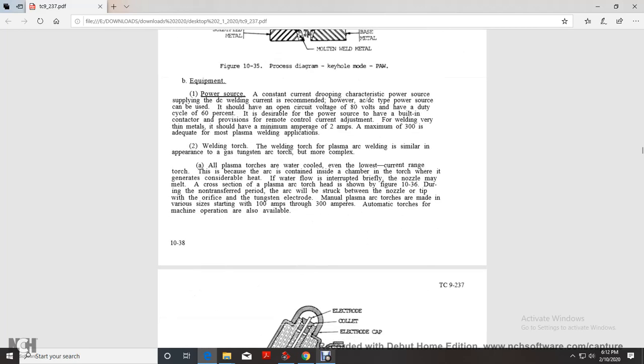Equipment. The power source is a constant current, drooping characteristic power source supplying DC welding current, which is recommended. However, an AC/DC type of power supply can be used. It should have an open circuit voltage of 80 volts and a duty cycle of 60%. It is desirable for the power source to have a built-in contactor and a provision for a remote control circuit, so that current can be adjusted remotely. For welding thin metal, it should have a minimum amperage of 2 amps, with a maximum of 300 amps for most plasma arc welding applications.